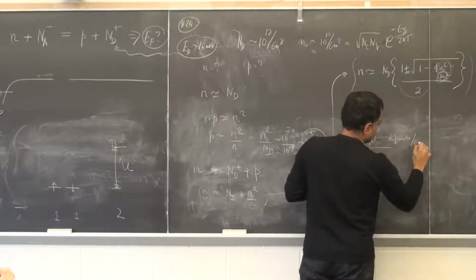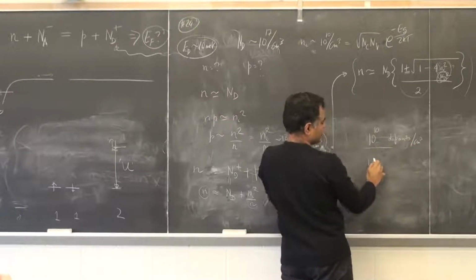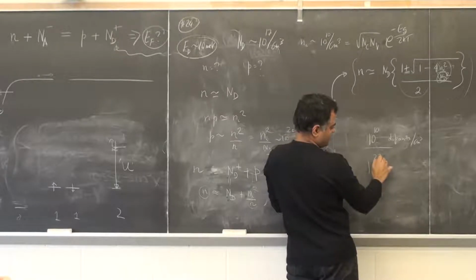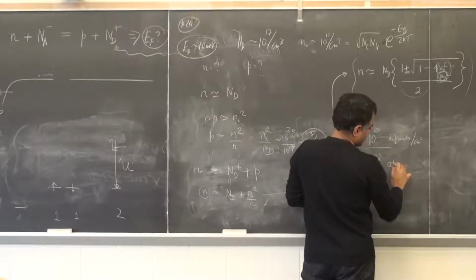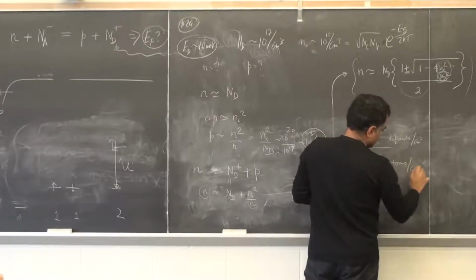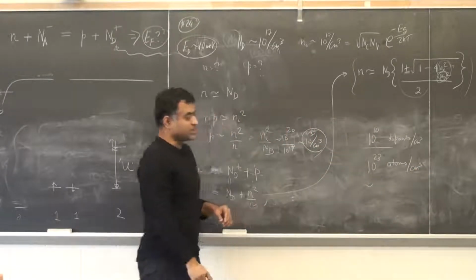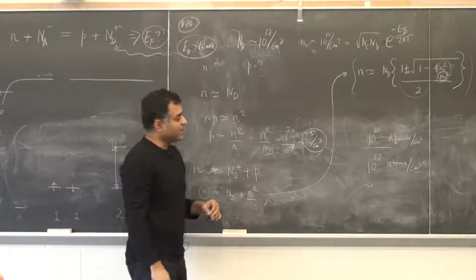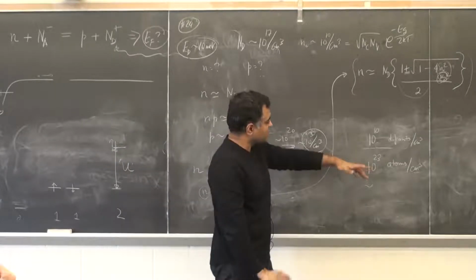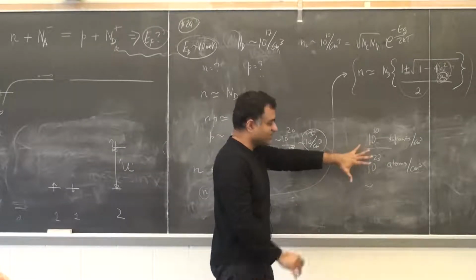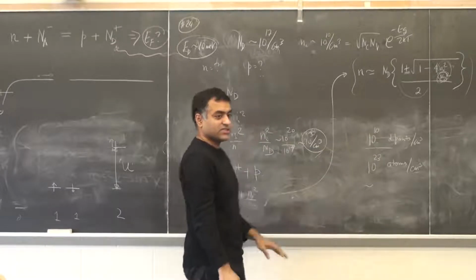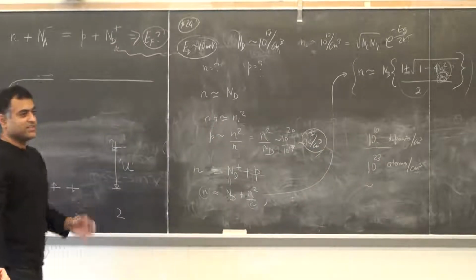per centimeter cube divided by how many atoms in the crystal, 10 to the power 22, 23, atoms per centimeter cube. So you can see the purity level here is 1 in 10 to the power 13, so it's very, very high. So silicon is close. You can actually measure intrinsic properties in silicon. It's the purest material ever synthesized on Earth.